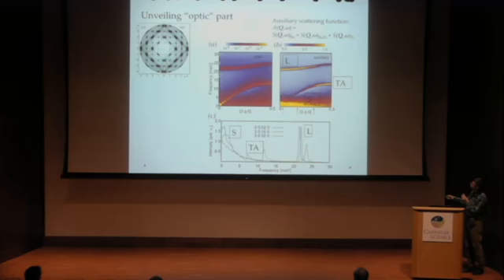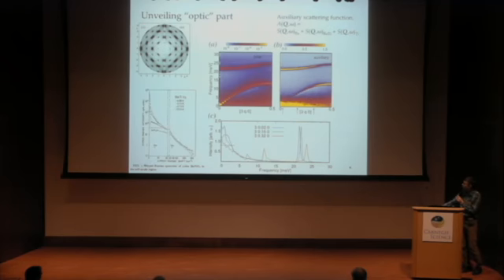And this is done because we want to look at the spectrum at that point, for example, close to the zone center. And close to the zone center, you get this kind of spectrum. So this is from the Slater mode, the titanium motion. There is an acoustic branch here, and there's the motion of the barium. And the characteristic frequency of that mode corresponds to one which is measured, let's say, in infrared or hyper-Raman spectroscopy. So we know that this mode is really the soft mode which describes the dielectric constant of cubic barium titanate.